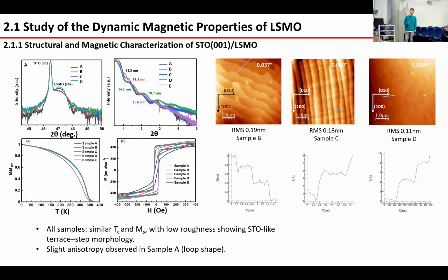We study the dynamics. So before studying the dynamic magnetic property of LSMO, we need to find the real relation between the dynamic property and the LSMO structure. So we grow a series of LSMO on top of STO 001. We show that the X-ray theta-2theta scan curve shows a clear LSMO peak regardless of the sample, and the thickness is from 10 to 15 nanometers.